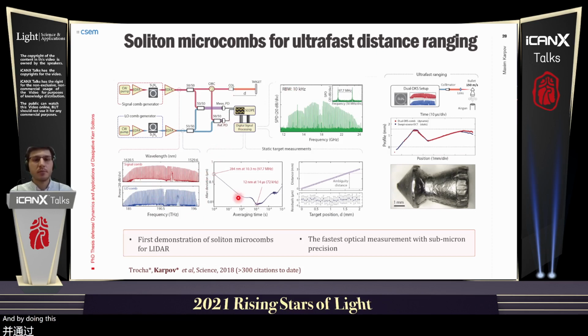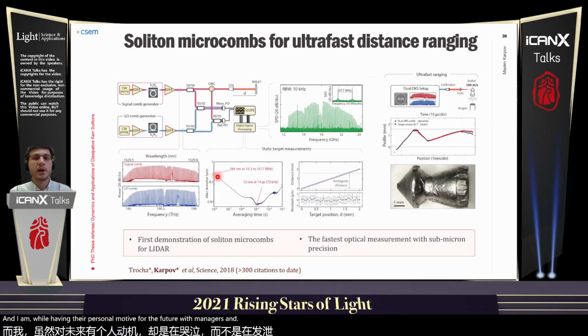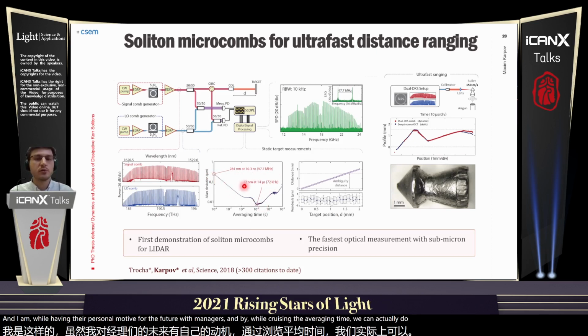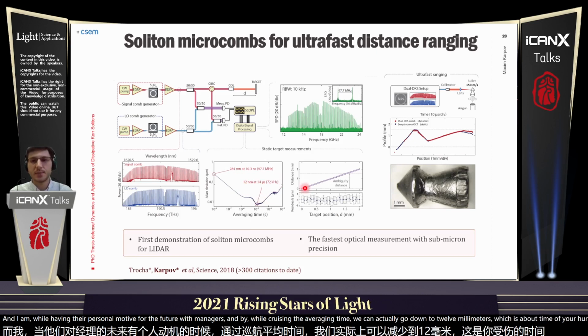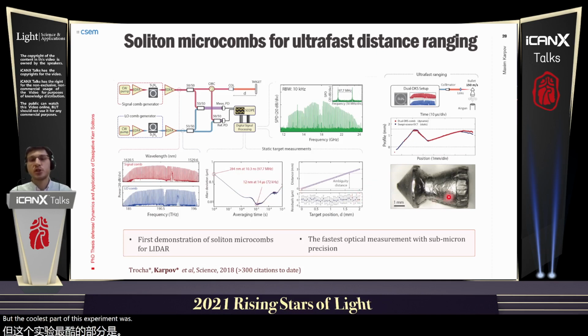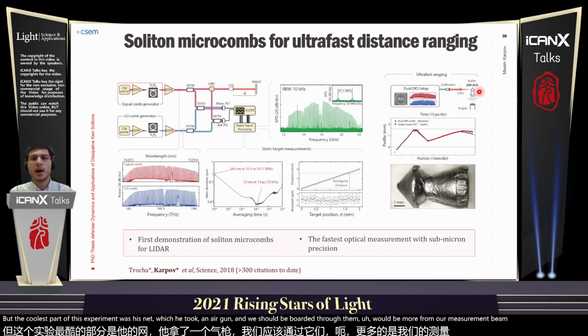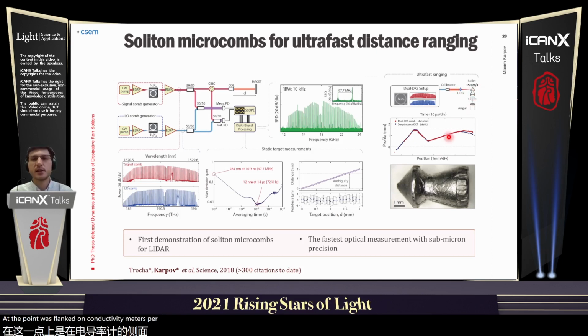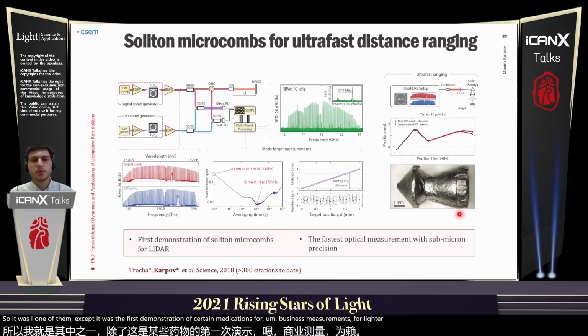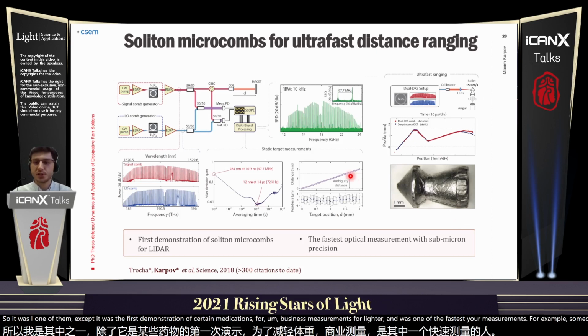By doing this, we were able to achieve very high acquisition speeds of about 100 megahertz, while having a precision on the order of 300 nanometers. And by increasing the averaging time, we can actually go down to 12 nanometers with about 100 kilohertz sampling rate. But the coolest part of this experiment was that we actually took an air gun and shot a bullet through our measurement beam. The bullet was flying around 150 meters per second, and we were able to precisely recover its profile. It was the first demonstration of soliton microcombs for distance measurements and LiDAR, and one of the fastest optical measurements with sub-micron precision.